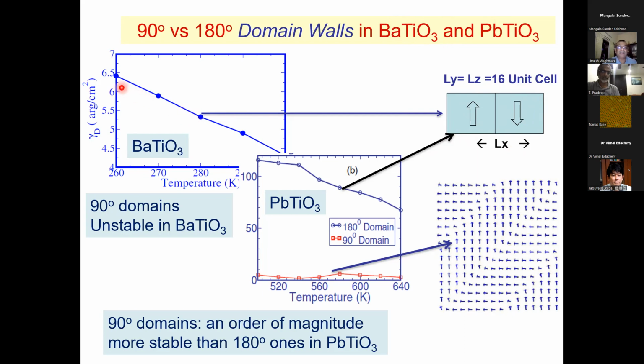In barium titanate, you have this 180-degree domain wall where the polarization is in opposite direction in adjacent domains, whereas in lead titanate, the domain walls are 90 degrees type of orientation, and 180-degree domain walls are much more expensive than the 90-degree domain walls. And you see, this is also, of course, consistent with what is observed experimentally.